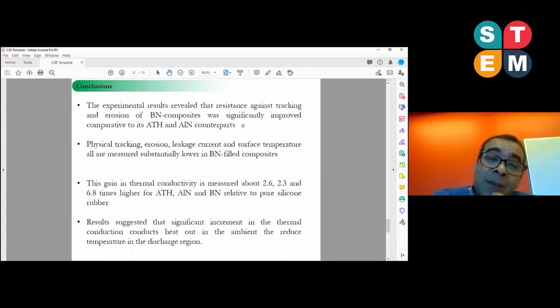The gain in the thermal conductivity in the BN is measured about 6.8 times. 6.8 times higher thermal conductivity is observed relative to 2.6 and 2.3 times in ATH and ALN. So that increment is very huge. It's a very good increment. So that's why we clearly seen a huge impact in the experimental result.